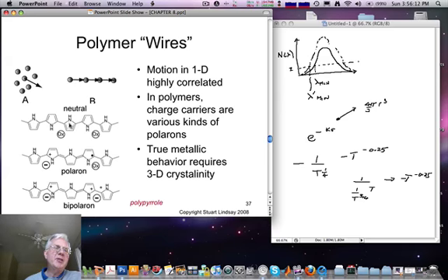Well, this illustration at the top here is to show you that the mechanism of electronic conduction changes drastically if you go from a two-dimensional material, where an electron can presumably always find an unoccupied site randomly, to a one-dimensional material, where if an electron is to move from this site to this site, then an electron occupying this site must necessarily move from this site to the next. In the language of physics, this is called a transition from a Fermi liquid, as we discussed in Chapter 7, to here what is called a Luttinger liquid, if indeed there is mobility in the material.